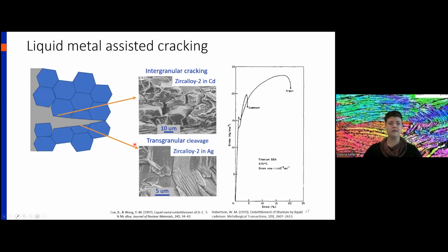So liquid metal assisted cracking looks a lot like this. You can get intergranular cracking or transgranular cleavage, depending on what system you're looking at. So these are both zircaloy, but in cadmium, you get intergranular cracking, and in silver, you get transgranular cracking. In both cases, you get this characteristic stress strain behavior where overall, your yielding behavior is similar with and without the presence of liquid metal. You may actually get a slight increase in yield strength because of solute effects and some solid solution strengthening in the liquid metal. However, you get a catastrophic reduction in ductility.